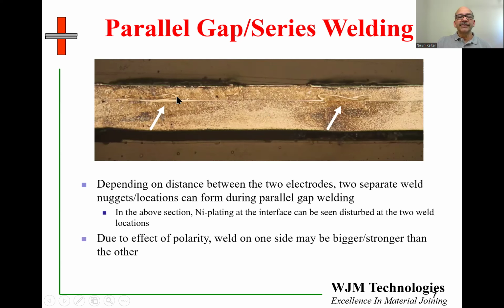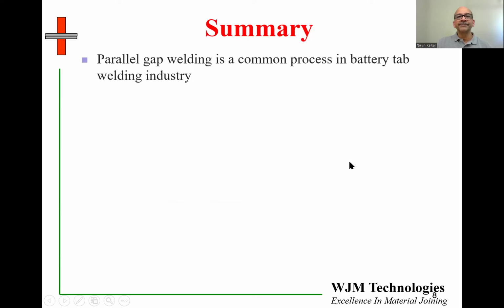You can also notice, in the metallurgical cross sections as well as in mechanical testing, that one of the welds on one side is slightly weaker than the other. And this is due to the effect of polarity, which we will review in another of the videos in this playlist. You'll find that one side of the weld is weaker than the other because of the directionality of DC current. And this is not unusual. This is quite common in parallel gap resistance welding.